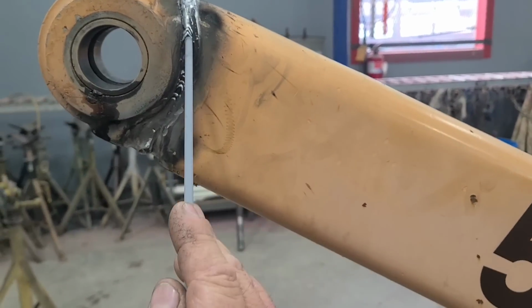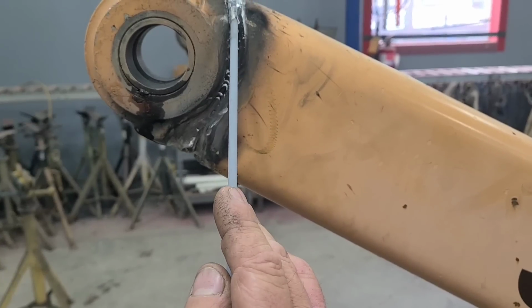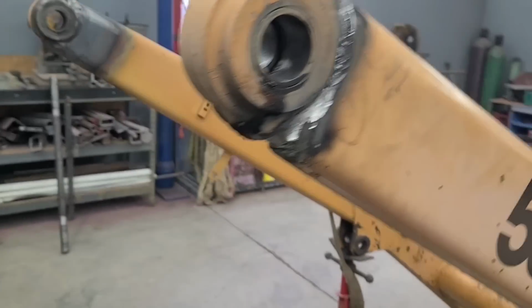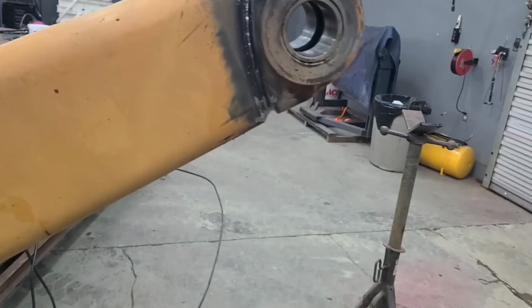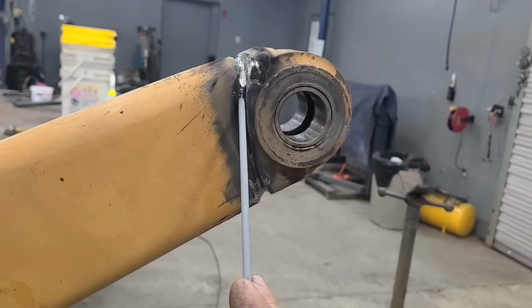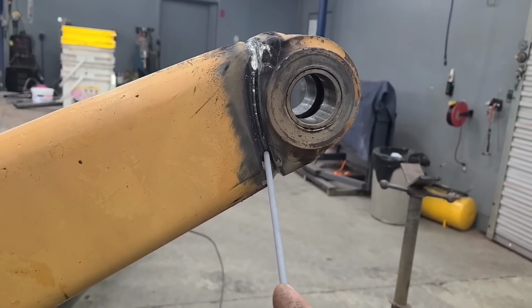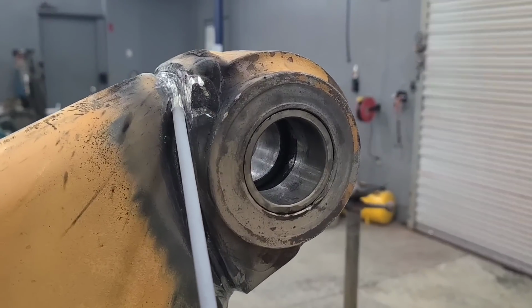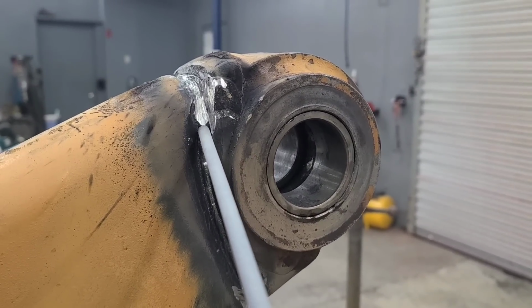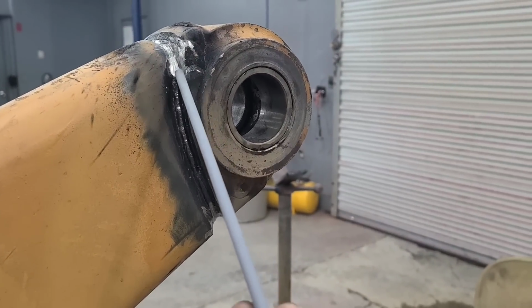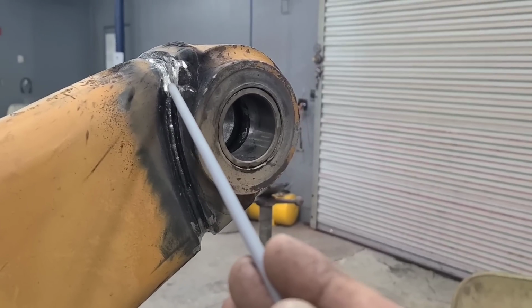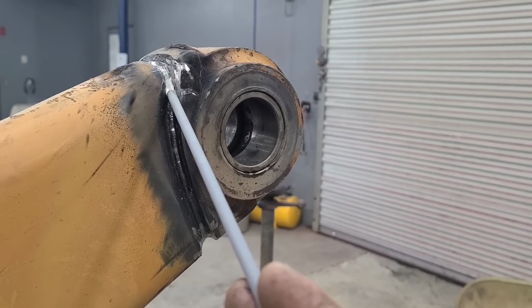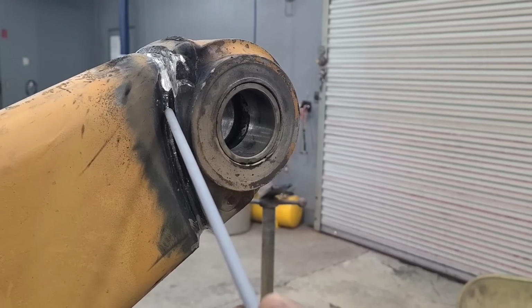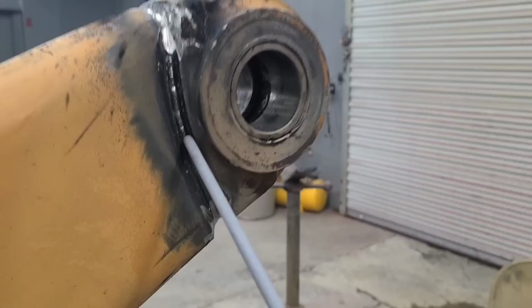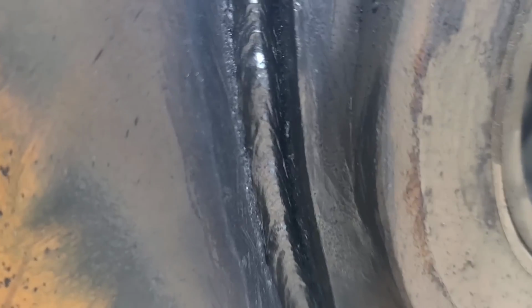Now, all the way down this side, I just pretty much got a standard hot pass, scratch and pause, scratch and pause. Now over here, this side, the MIG weld that I had under it must have been a little bit weak, because as soon as I began to scratch and pause, I blew right through there. So when I blew through there, it was time to go into a root bead mode, not a hot pass mode. So I didn't scratch and pause any longer. I just press and move. And as I pressed and moved, I made this bead. Now this is very much like a root bead.